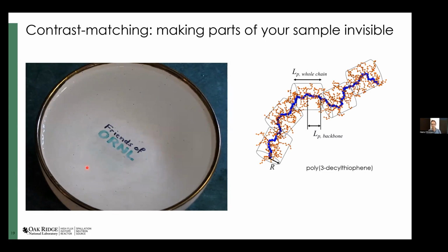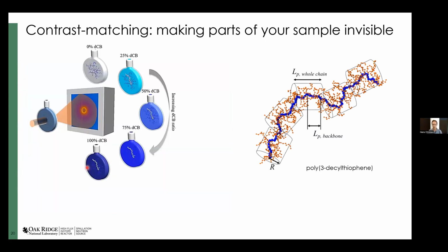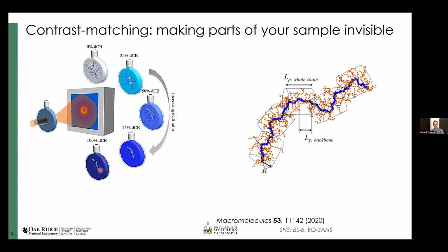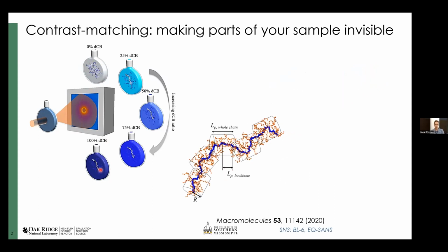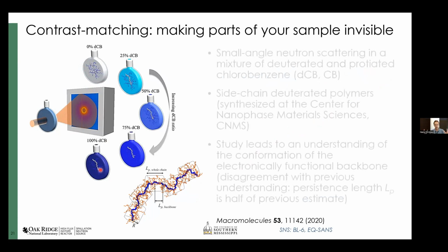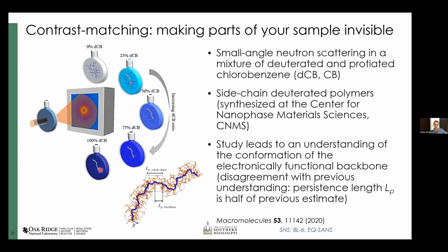And you could do that by not making the side chains using hydrogen, but using deuterium, and then using different solvents to look at this. And depending on what the solvent is, whether it's water, or in this case, I think it's actually benzene, a hydrogenated benzene, the whole polymer is visible. Or you can go to deuterated solvent, and the backbone is visible. And if you do that, that will tell you the shape just of the backbone. The outside has become invisible. And that leads to an understanding of what this conformation length here is and how this polymer in particular actually deforms in real situations.